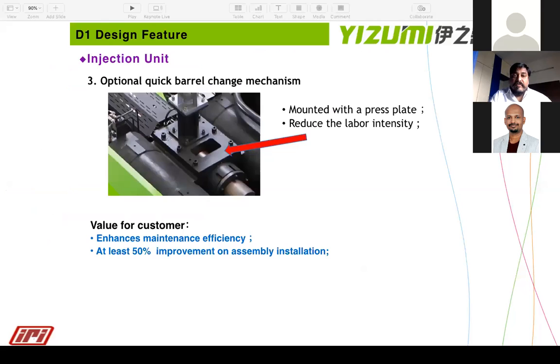Okay. Also, we have developed a new injection unit with a quick barrel change mechanism as an option. In case you are using different materials, particularly transparent material, after a normal black material it's very difficult to get the same quality, because every time you have to purge out a lot of material. So some customers now prefer to use a separate screw barrel for clear materials, particularly acrylic and polycarbonate transparent, and another for PP glass-filled or black or dark colors. So nowadays it has become a requirement that the screw barrel has to be changed quickly. So we have developed a quick barrel change mechanism.